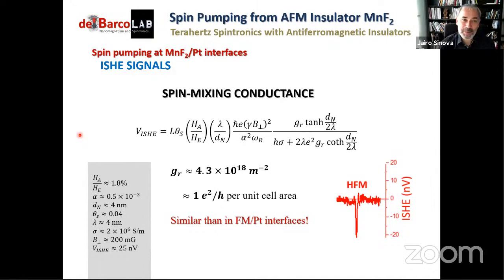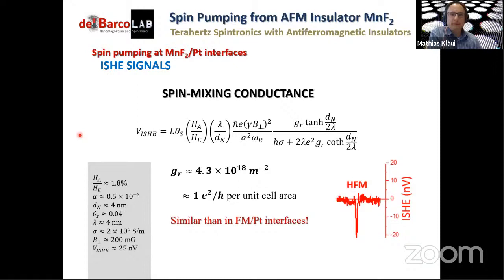Yes. So firstly, thanks for the nice talks. I'm also a humble experimentalist, so just easy questions. You mentioned that spin pumping only works for circularly polarized magnons because only they carry angular momentum. However, in the easy plane phase of an antiferromagnet, the polarization depends on the K vector. So for small K vectors, you have mostly circularly polarized magnons, and then at the Brillouin zone boundary, you go to linearly polarized magnons. So I wonder, is there a way to quantify the polarization, the ellipticity, and then from that learn which magnons contribute to the pump current?